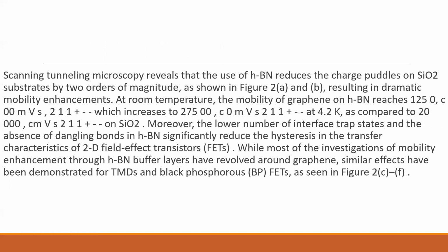At room temperature, the mobility of graphene on hBN reaches 125,000, which increases to 275,000 at 4.2 K, as compared to 20,000 centimeters squared per volt-second. Moreover, the lower number of interface states and the absence of dangling bonds in the hBN significantly reduce the hysteresis in the transfer characteristics of 2D field-effect transistors, FETs.